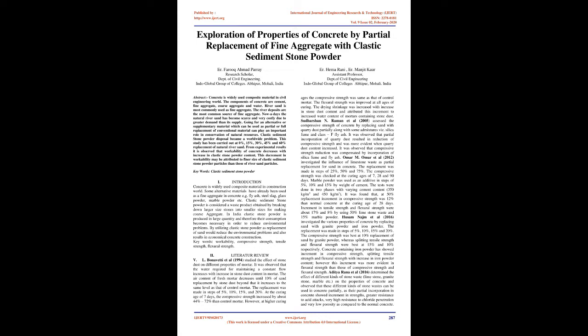The replacement was made in steps of 5%, 10%, 15%, and 20%. At the curing age of 7 days, the compressive strength increased by about 44%, 72% than control mortar. However, at higher curing ages the compressive strength was same as that of control mortar. The flexural strength was improved at all ages of curing. The drying shrinkage was increased with increase in stone dust content, attributed to increased water content of mortars containing stone dust.